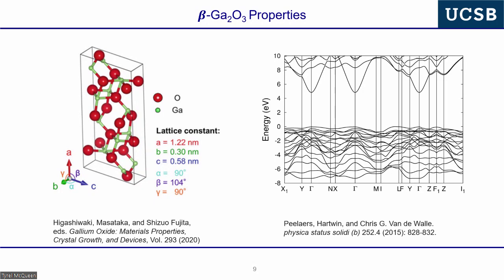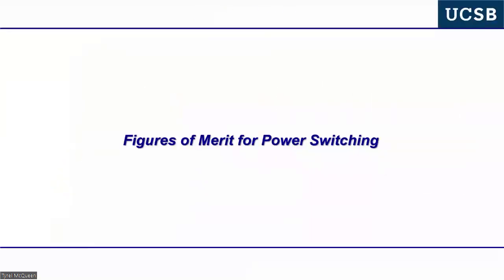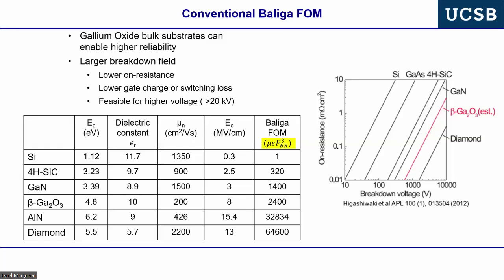Okay, and that's experimentally measured with my collaborator Saulius Marcinkevičius at KTH in Stockholm, and that's on the order of half a picosecond. Okay, what you would expect for the motion from acoustic phonons. And so now we're going to look at, if we have these properties that I showed a couple slides ago, how we look at possible figures of merit for power switching.